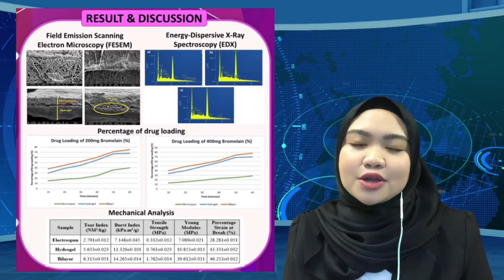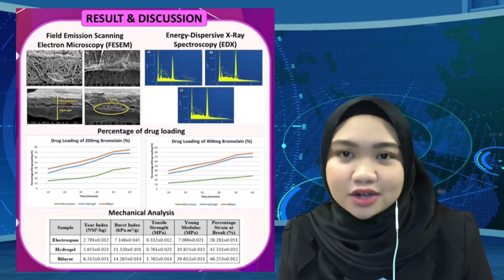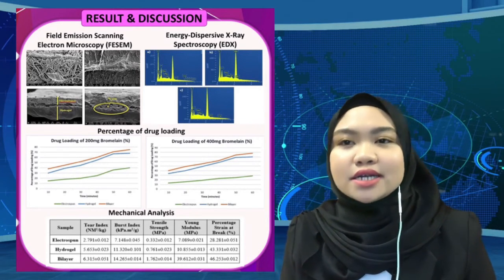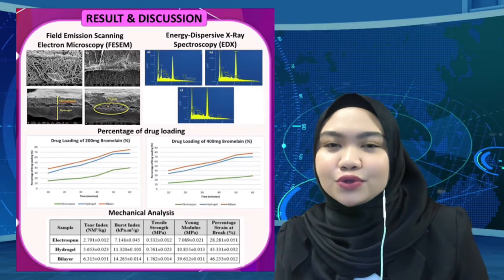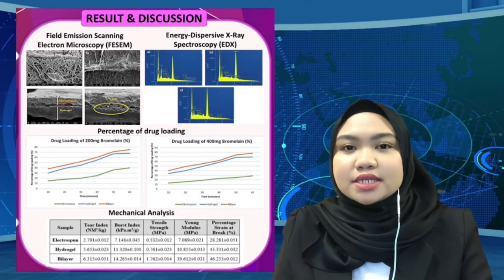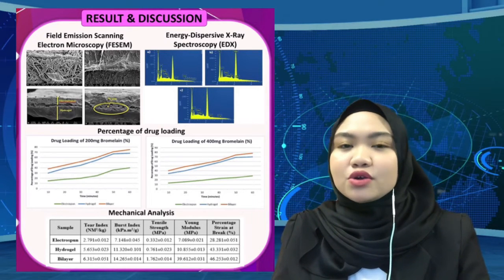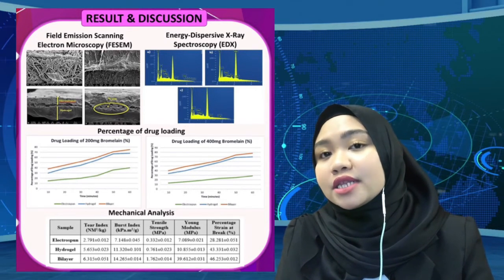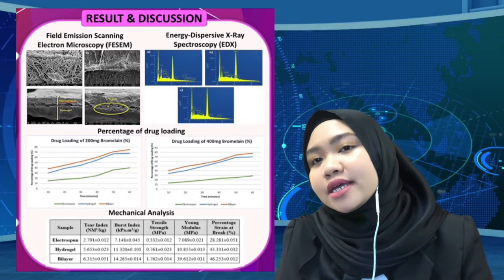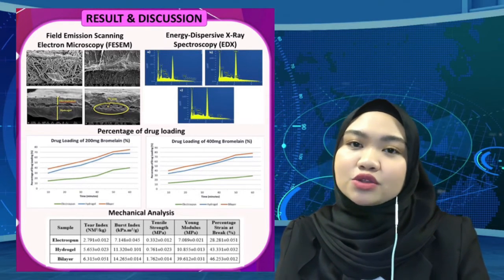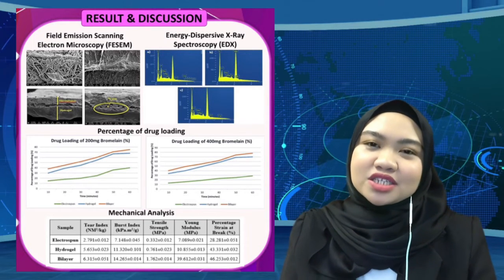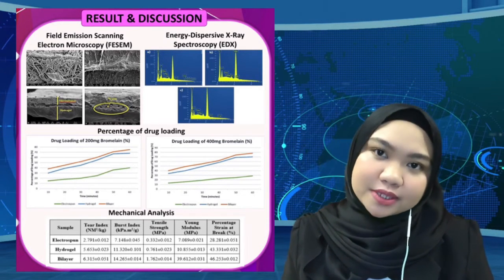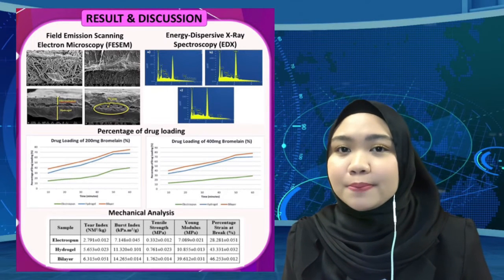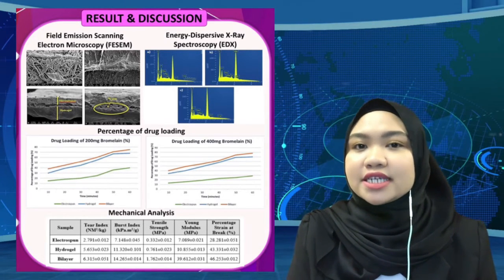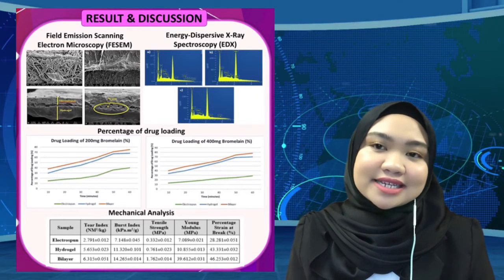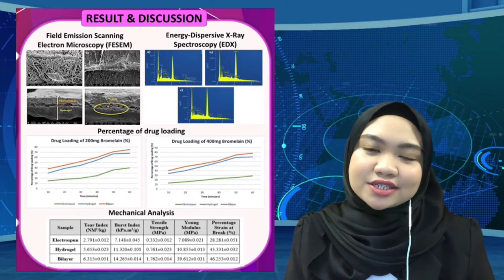81.15% and 56.81%, while the Young modulus remarkably increased by 82.10% and 72.60%. The last one, the percentage strain of the bilayer composite, also increased by 70.97% for electrospun and 2.92% for hydrogel, to 46.25%. So overall, the bilayer composite mechanical properties meet the requirement for tissue application in wound healing in terms of tear index, burst index, tensile strength, Young modulus, and percentage strain at break.